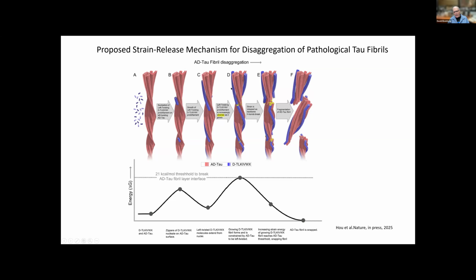And eventually that strain builds up so that it becomes equal to the energy of breaking the fiber, which we estimate to be about 21 kilocalories per mole. So here's a point where it's going to break because the fiber has grown enough to have a great strain. Now it snaps, and both fibers snap into pieces, and these are the products which don't reassemble because they're still bound to fibers of the peptide or the small molecule.